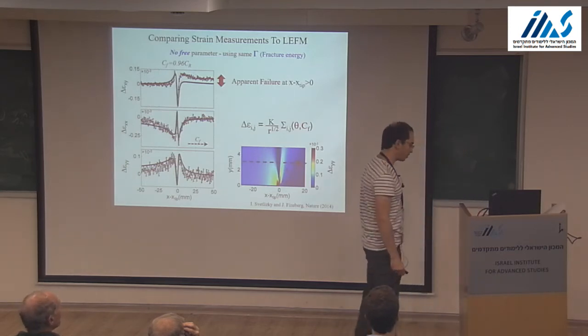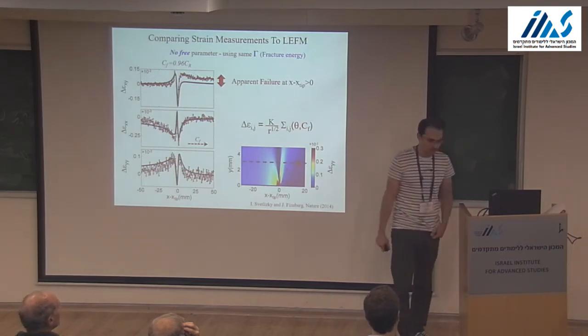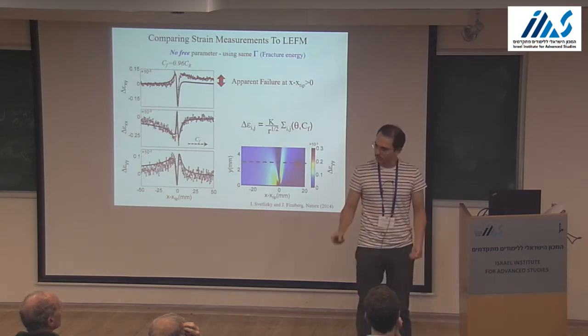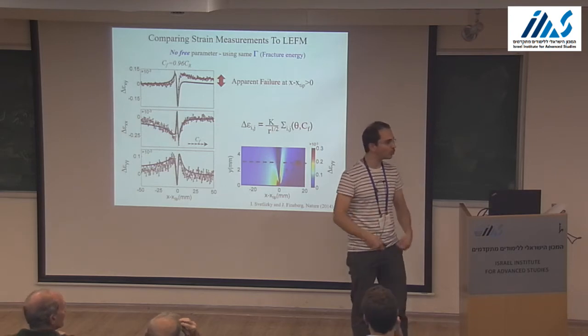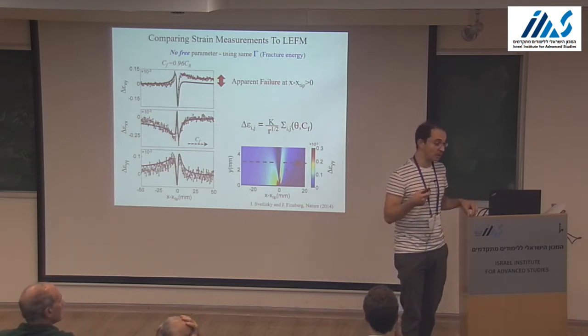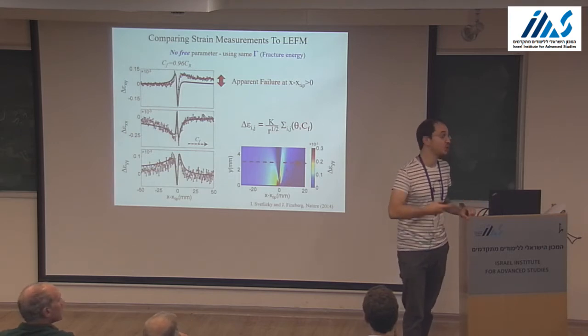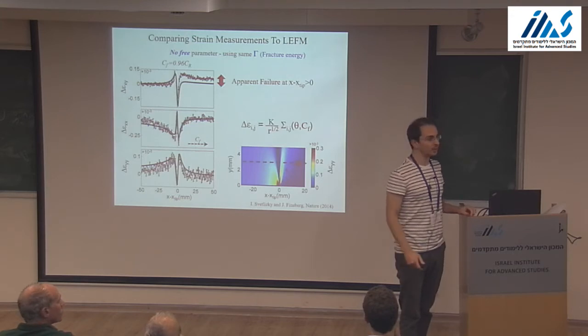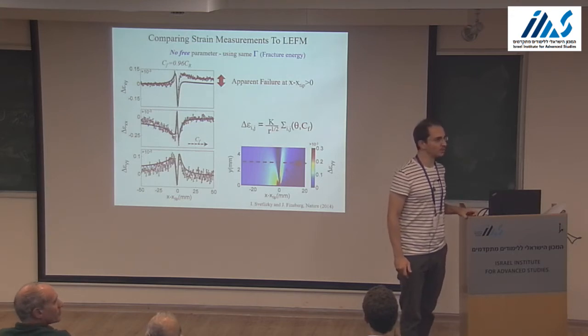We use a bit of detergent and then isopropanol, wait for an hour or two, and then do the experiment. We intend, in the future hopefully, to change the roughness of the interface, for example. Regarding lubrication, tomorrow Elsa will tell you what happens. I don't want to give spoilers.